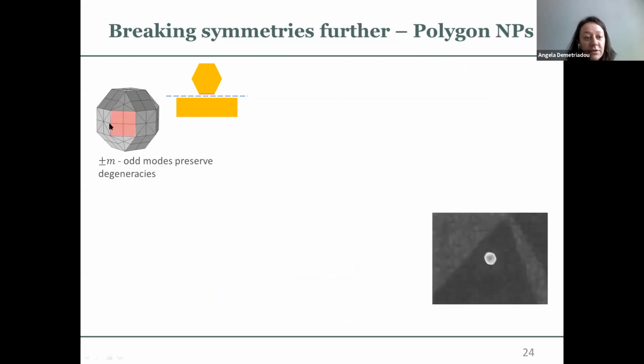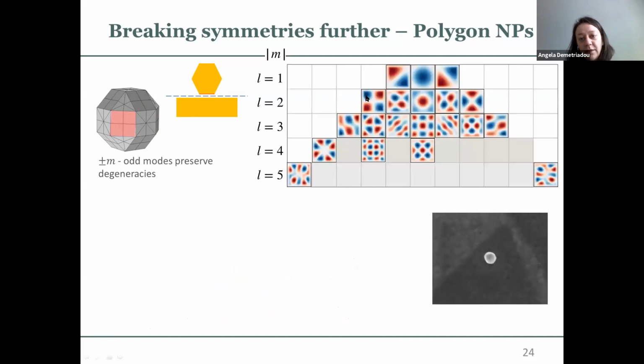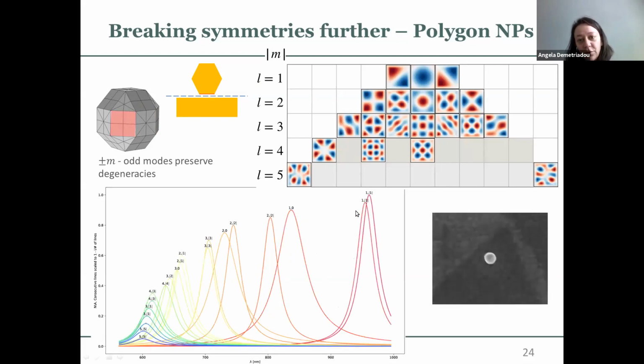However, if I pick this facet to assemble it opposite to the mirror, I'm breaking that symmetry. And again, this is a very similar mode as to what we had before. And I'm breaking that symmetry, so this and that mode are not degenerate anymore. So it depends a lot on what's the neighboring facet around the one I'm assembling opposite to the mirror, because of the electrons getting scattered from the edges of the facets as they travel on the surface of the nanoparticle. So they will have a different path on this direction than on the other direction.